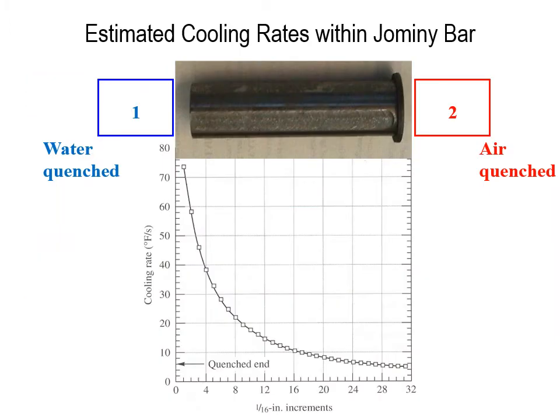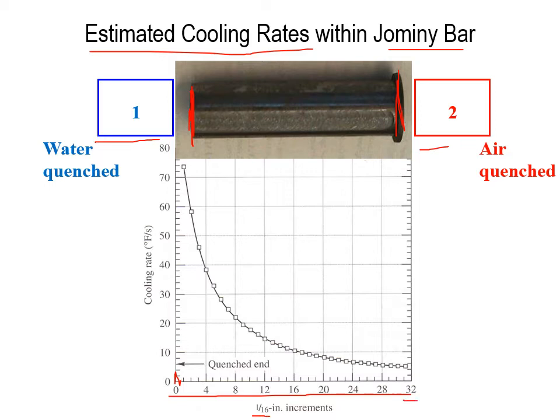So we can see in the chart shown here, we have the estimated cooling rates within the bar. If we take a look over on the left-hand side, this is the side of the bar that is water quenched at the bottom where the water jet is, and the right-hand side over here is the top where it's air quenched. Our x-axis here is our distance starting at 0 away from the end of the water quench all the way up to 32 over here, where these increments are in 1/16 of an inch. On our y-axis, we have the cooling rate, which is in degrees Fahrenheit per second.